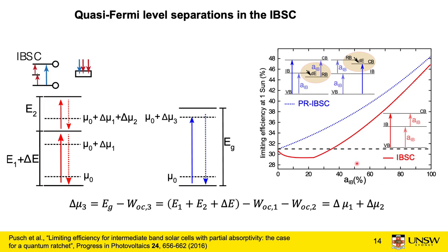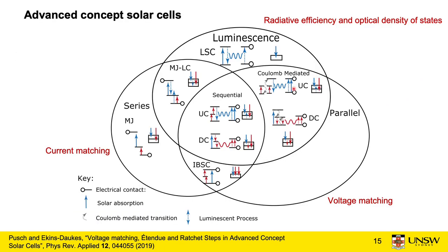The same principle also applies to optical upconversion. In fact, all efficient upconverting materials have an intermediate dark state. We can also have a second transition that is mediated by Coulomb interaction between electronic excitations. I call those therefore Coulomb mediated. The interaction could, for example, be of Auger type in semiconductors, but generally any interaction that transfers energy from two excitations onto one excitation or vice versa.